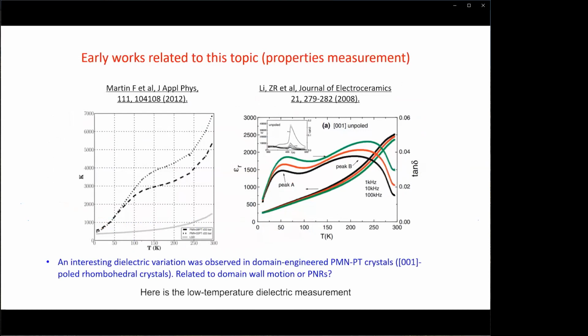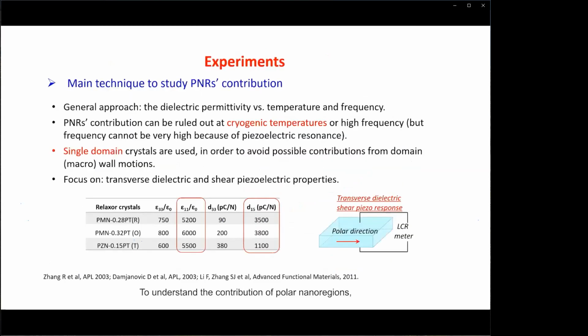Here is the low-temperature dielectric measurement on domain-engineered PMN-PT crystals. We can see that there is a very interesting dielectric variation at low temperature, which deviates from the phenomenological calculation. The authors of these papers argued that this variation may be related to the polar nanoregions. To understand the contribution of polar nanoregions, we did cryogenic experiments for Relaxor-PT crystals. Since the contribution of polar nanoregions can be ruled out at low temperatures, we selected single domain crystals for this study because we want to exclude the possible contribution from domain wall motion.